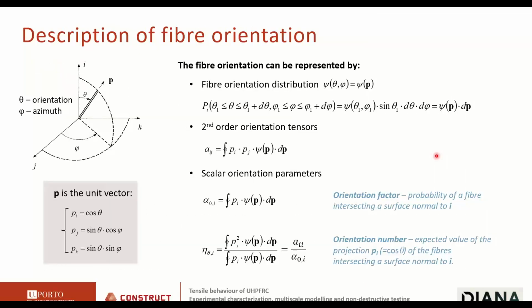So we need to have a description of the fiber orientation. This can be very complicated, but at the end, we will need only very simple scalar parameters. The orientation of a fiber can be described by two angles. The orientation angle, okay? Imagine that the JK plane is your crack, and theta equal to 0 is a fiber that is perpendicular to your crack, okay? And theta equal to 90 degrees is a fiber that is parallel to your crack, so it's not working, okay?